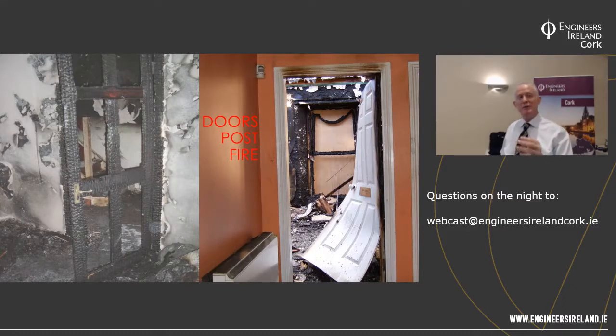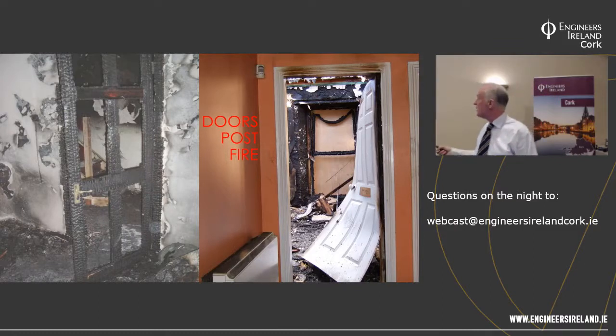So if it burns at two thirds of a millimeter a minute, or with good hard work maybe 0.5 millimeter a minute, very rapidly it burns through the panels, and then you're left with this situation. In this case, the door held very well, but the back of the door, most fire doors are just solid chipboard in the middle. Chipboard burns at around 1 millimeter a minute once you get at it. So effectively, if you have 45 minutes of chipboard, after 30 minutes you don't have enough left, and once the door was kicked open by a firefighter or whatever, the back of it is gone. I thought they were interesting photographs to show you, particularly about the panels.